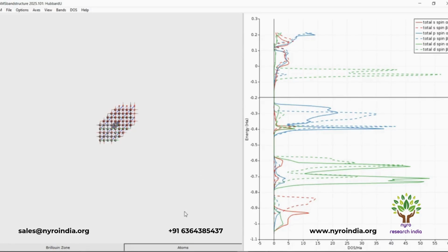The atom-wise representation we can see in the colored region. For spin polarized calculations, the partial density of state will be spin dependent. We can examine the partial density of state for spin up and spin down electrons on the nickel atoms to understand the origin of the magnetic moments and the antiferromagnetic alignment. So it's about that spin polarization. And the partial density of state of the two nickel atoms in the unit cell with opposite spin will be shown mirrored, reflecting the d band occupancies.